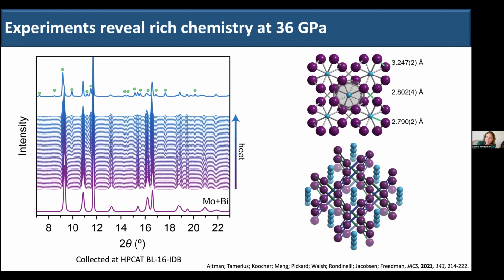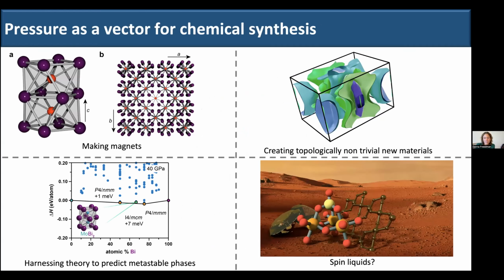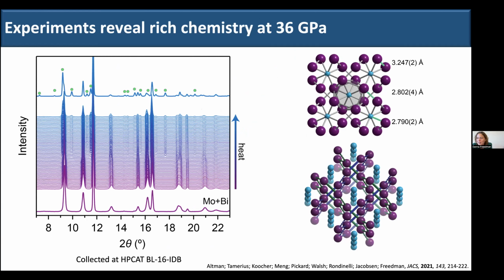So we went after the calculations and we found that there is indeed this molybdenum bismuth 2 phase. And this is an example of a compound that absolutely doesn't even come close to persisting at ambient conditions. But anyway, we were able to perform calculations to predict and synthesize this new phase that does match approximately the structural parameters from the theoretical calculations. So I think that is probably a good point to stop and ask for questions.